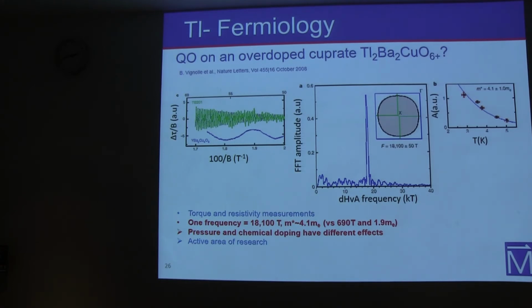But the effective mass is very different compared to the different systems. Yes. So for that compound, thallium, the effective mass is 4.1, and what we get is of the order of 1, 2. The results are completely different. So it's either you say that their interpretation that thallium is the overdoped analog of YBCO is wrong, or we say that there is something happening with pressure that can also give us different results.